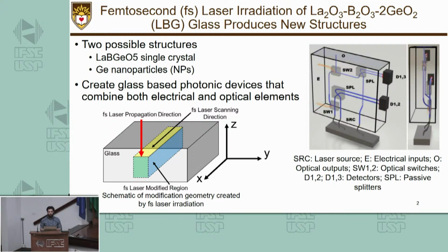And what we're able to do with the femtosecond laser, by focusing it in the glass, is create these line modifications. The two modifications we make are single crystal lanthanum borogermanate, and the work that I'm working towards is creating a continuous channel of germanium nanoparticles. And the goal is to combine these two components, both electrical and optical, to create new photonic-based devices.